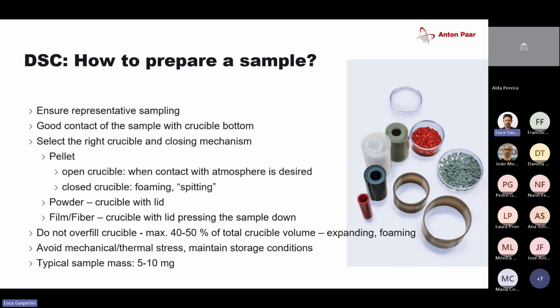But if I have a sample which during the heating might be foaming or spitting or expanding a lot, then I'd rather put a lid on to make sure that the sample doesn't creep out of the crucible and contaminate my sensor, which is something that I want to avoid, because then I would need to clean the furnace. And I'm not a very big fan of cleaning, whether it's a DSC or my room at home, so not really.